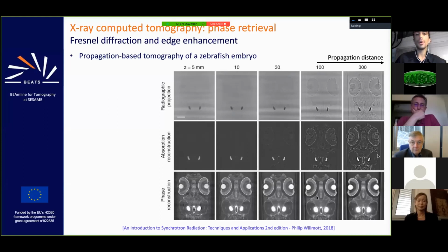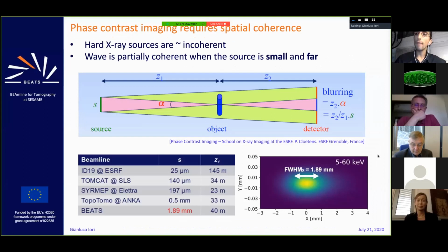So one of the requirements to operate in phase contrast is actually to have spatial coherence. And X-ray sources, particularly when the source has a finite size, work as incoherent sources. The way this is optimized at synchrotron facilities is to work with very long beamlines and to reduce the size of the source. So in the table, I'm collecting information on other tomography beamlines in Europe, compared with BEATS.